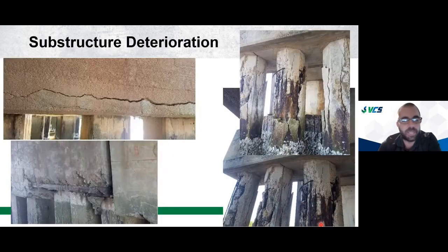And so if we look here, the two images on the left, these are the structure where the tidal action gets the water closer to the pier cap. The pier caps are close to the water. And so we're seeing a lot of damage in the bottom of the cap and the top of the piles. Whereas on the taller structure, all of the damage is really focused on the piles. And again, that's where our marine tidal splash zone is going to be.